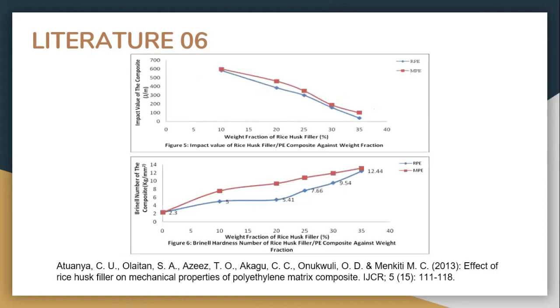With the use of pendulum impact testing machine, it was observed that there was significant decrease in the impact value, while there is a sudden increase in the Brinell number of the composite as the weight percentage increases. They then concluded that rice husk filler loadings increased the Brinell hardness, flexural strength, and flexural modulus, as well as the tensile modulus of the composite, but decreased its impact strength and tensile strength.